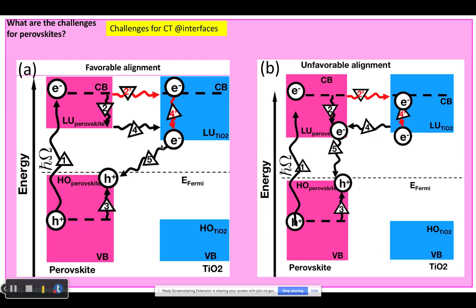So here the figure on the left shows favorable alignment that I just showed, and the figure on the right shows unfavorable alignment. So here the LUMO of the titanium dioxide is slightly higher than the LUMO of the perovskite. In this alignment, the transfer will happen, but it will not be stable. It will be very short-living. Upon charge transfer, it will come to the lowest available excitation, which will be the intrinsic perovskite HOMO to LUMO. So this alignment, even without computing any dynamics, will be unfavorable for charge transfer for photovoltaic applications.